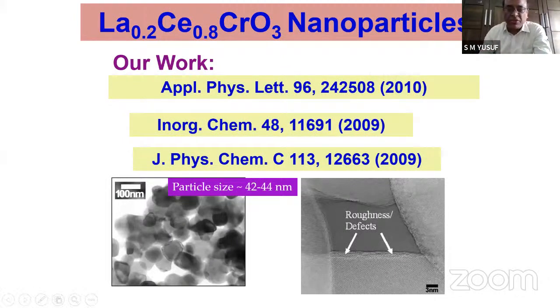Here you see the TEM image of single nanoparticles of the chromites. Here you basically see the core part and the surface, and at the surface you see structural disorder. This atomic disorder at the surface of the nanoparticle, here four nanoparticles on the copper grid, 1, 2, 3, 4 nanoparticles, you see the defects on the surface, and this kind of structural defect gives some kind of magnetic disorder state, prone to spin glass type. So an antiferromagnetic core and a spin glass like disordered magnetic state at the surface.